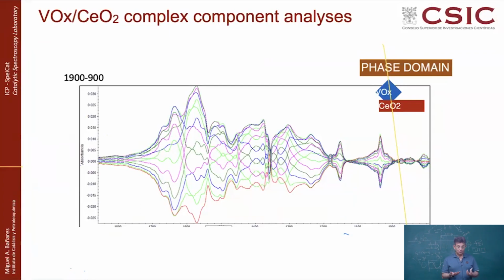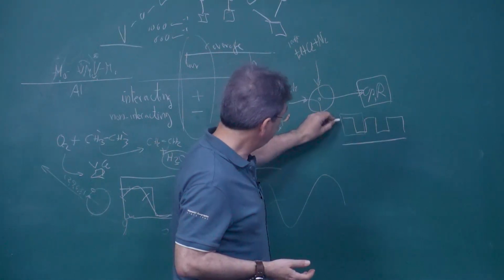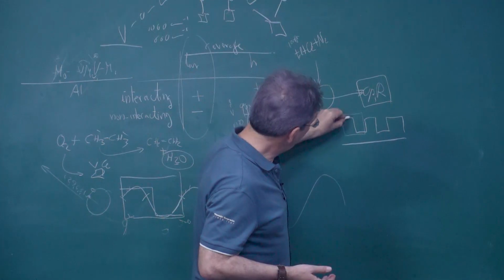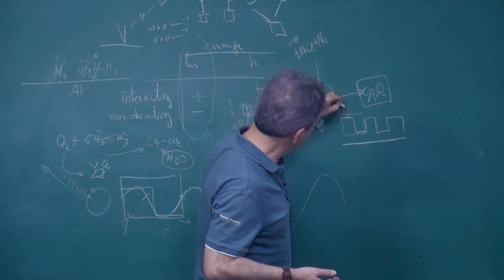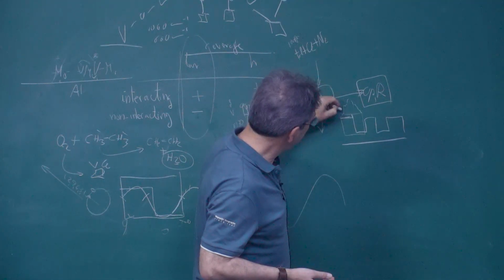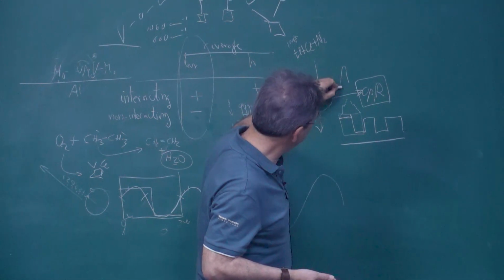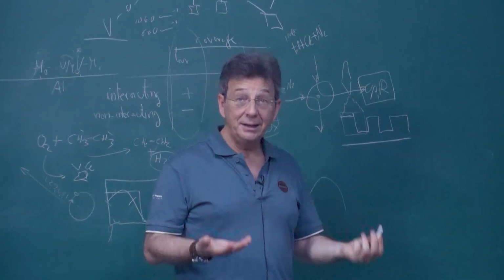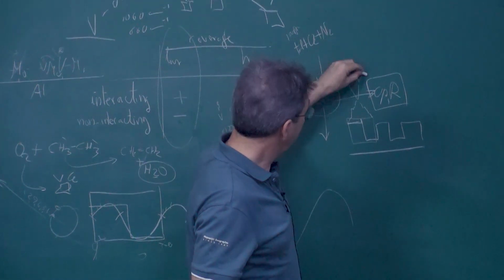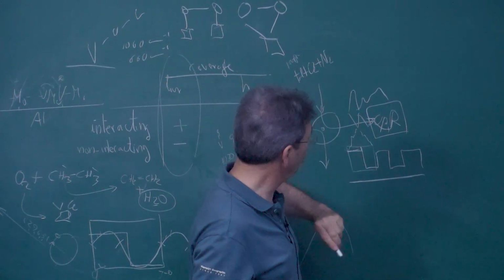But what do you get here? Well, you are getting not many bands, but the bands that change, the bands that are associated with reactive things that are happening. You get positive and negative, because during the cycle, sometimes you are feeding toluene, and when you feed toluene, maybe hydrocarbon species will increase. And then you stop toluene, and then the hydrocarbon species will decrease. So you will see that sometimes the intensities are growing, and sometimes decreasing. But any molecule doesn't have one band, it has like 2 or 3 bands that go up, or 2 or 3 bands that go down.